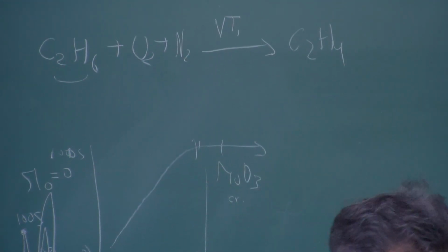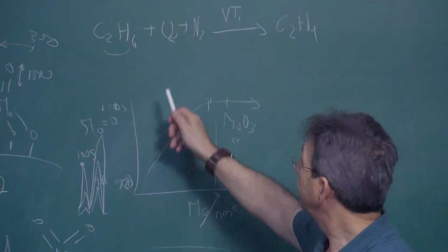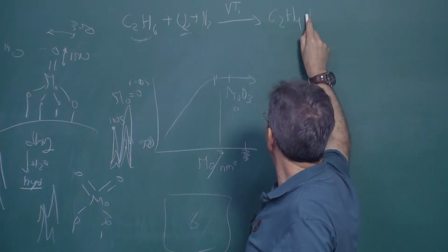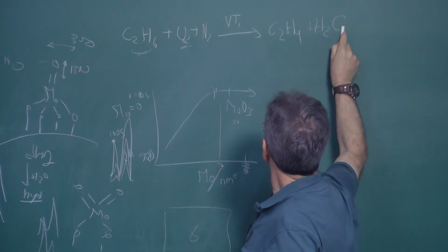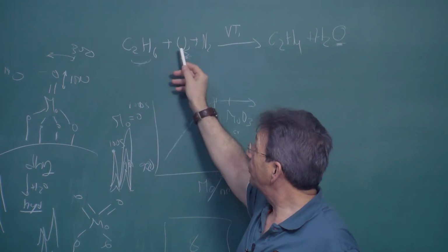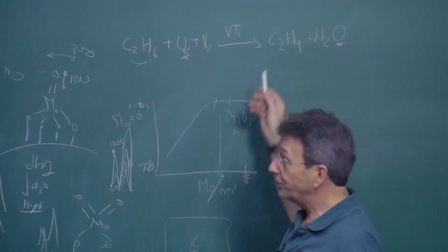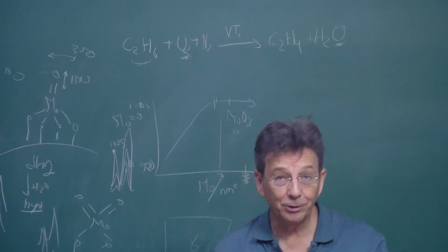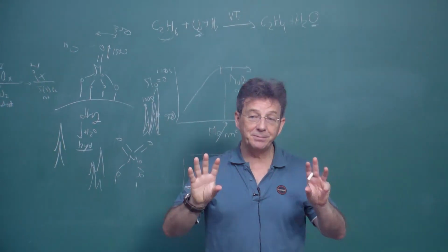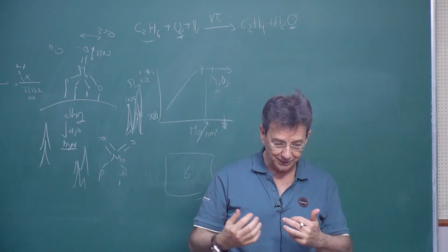You were telling about that on the first day. Lattice oxygen is being given, so this oxygen is going to react with this to produce water. So this oxygen comes from here, but it doesn't go directly. This oxygen is given to the vanadium, and the vanadium is giving a lattice oxygen to do this reaction. So it's a redox cycle going through the lattice. Now that means for a fraction of a moment, the vanadium is being reduced and reoxidized continuously. It's a redox cycle, reduction, oxidation.